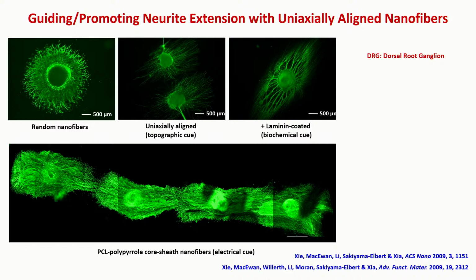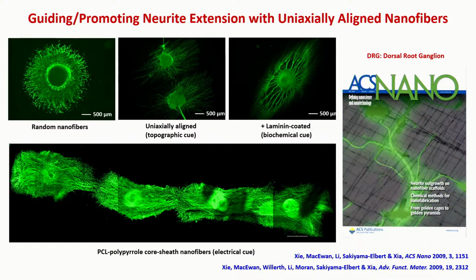And on the surface of these aligned fibers, you can add another laminin layer, actually. That's an adhesion protein that can further enhance the extension of neurites along the fibers through a combination of physical and biochemical cues. And you can also use some fibers that have good electrical conductivity, like polypyrrole. This is a conductive polymer, and you can also apply an electric field. So in this case, you can have electric field and physical guidance to have these neurites extended over a very long distance. This is like a centimeter of distance. In reality, these fibers can also be deposited into different patterns, and that can control the neural extension in such a complex way that eventually it may be possible to form neuron circuits.